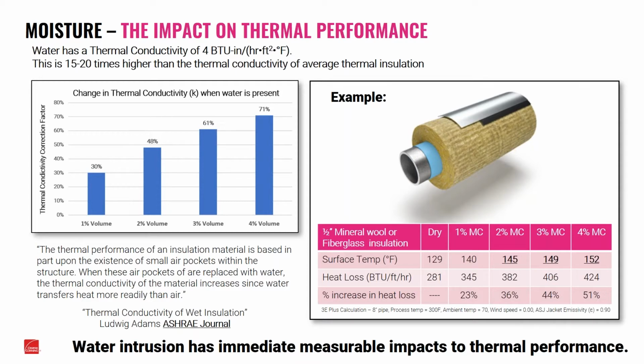Now, whenever we introduce just a little bit of moisture into this, we are changing the thermal conductivity slightly. So as we add up to either 1%, 2%, or 3% of water by volume, we know that it impacts it. We look at the impact of thermal conductivity, but really, I think the answer is over here on the right-hand side. We have a system where, let's say we do add 1% moisture content, and it does impact our thermal conductivity. Even just adding 1%, we have a 23% increase in heat loss in terms of BTUs from that system, and we've increased our surface temperature 11 degrees.